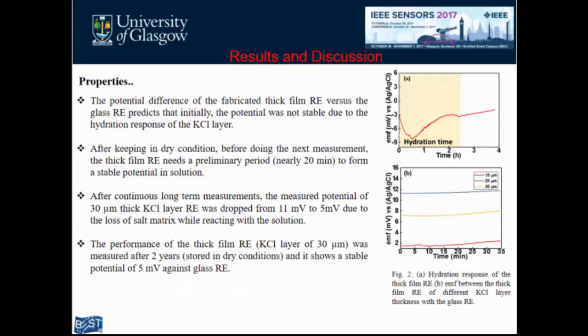After that, the basic study for any fabricated reference electrode is the stable potential, because we need a stable potential against a sensitive layer. So initially I did a measurement against a glass reference electrode. Here you can see the hydration. Initially, after fabrication, it takes some time to get stabilization because of the reaction of the water, and some initial drift is also there.